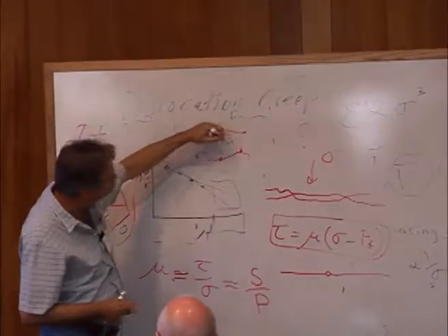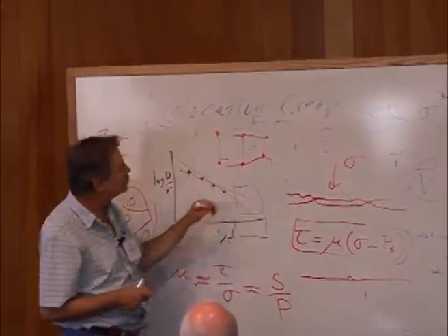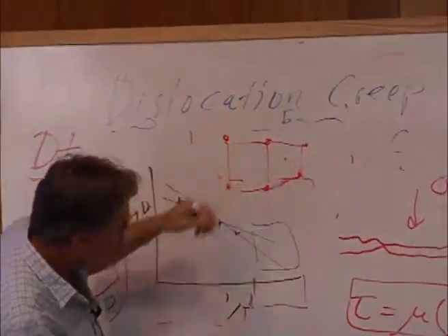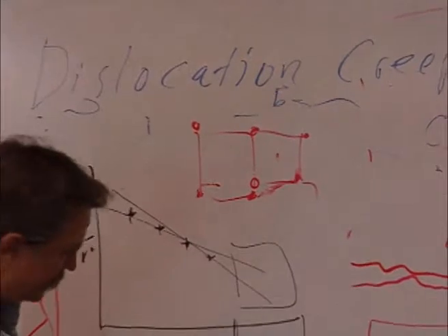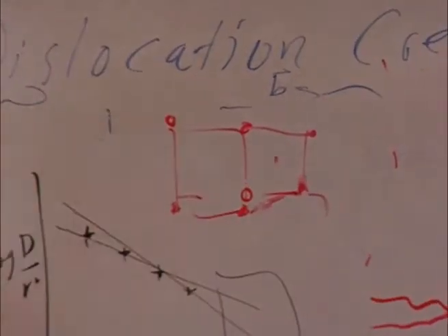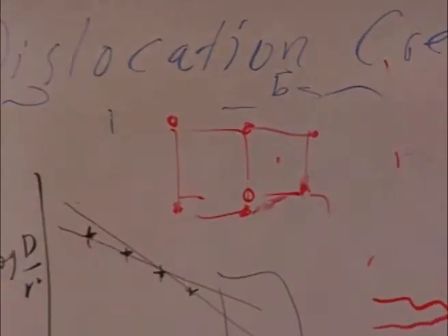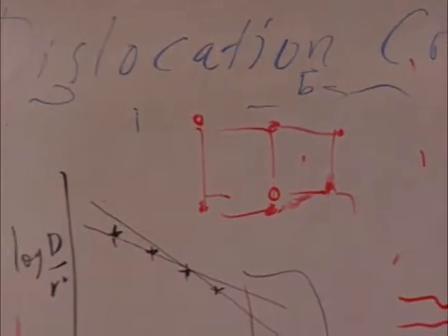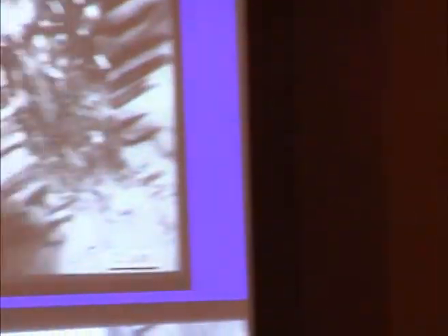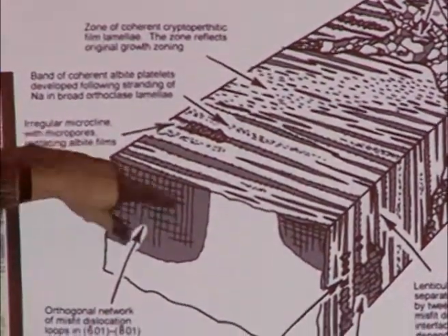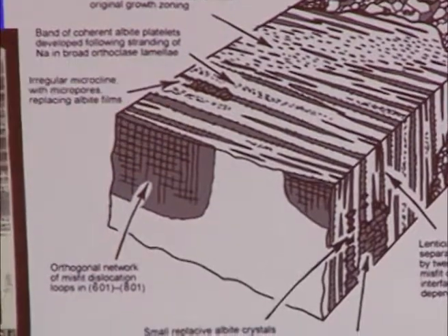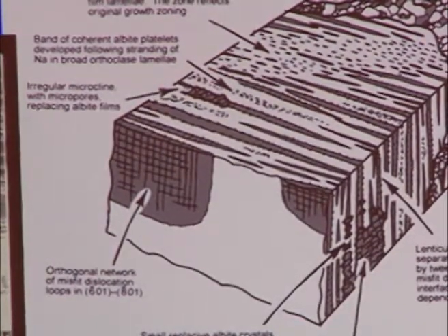At some point, you can just elastically deform that, but at some point, in fact, you actually break and you make a misfit dislocation, and that's what these little dots are. There, you do that actually in 2 dimensions. It's fantastic. It's like a series, like a chain link fence of tubes running adjacent to each of these little albite lamella.